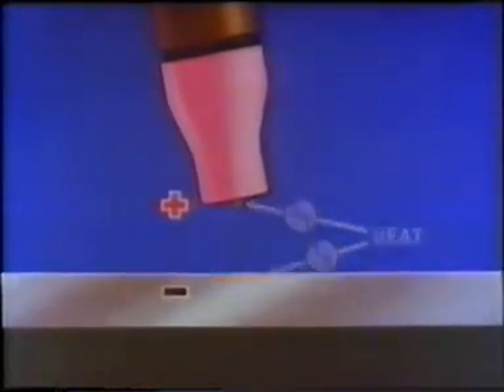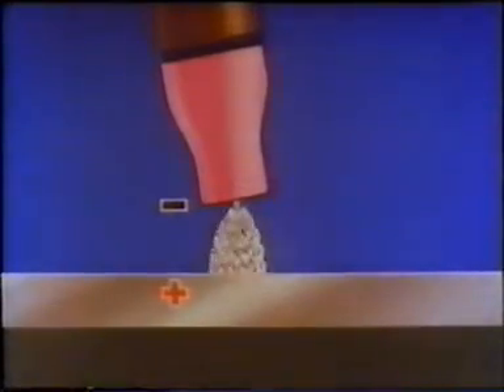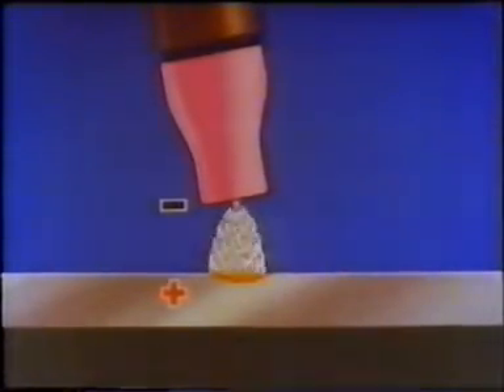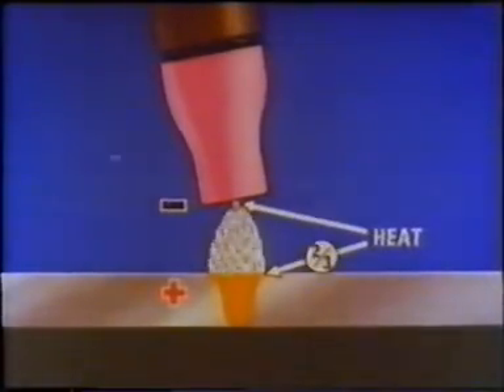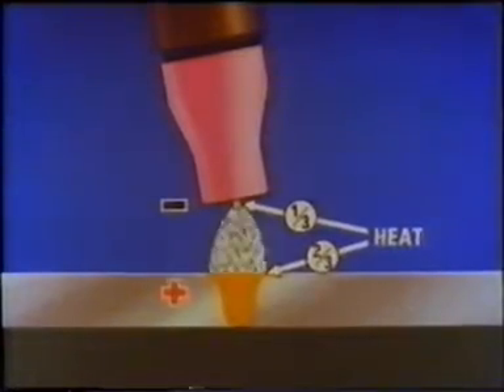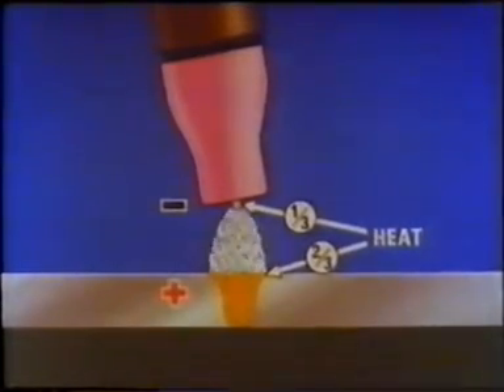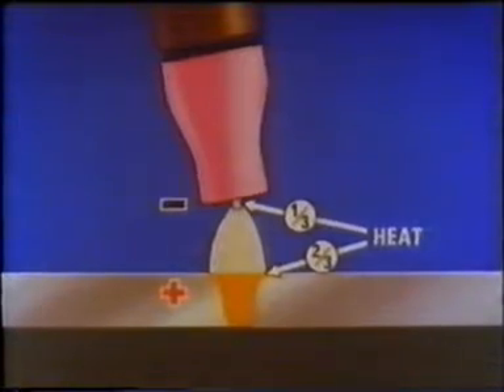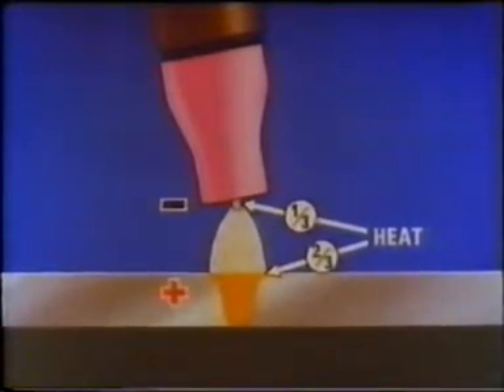With the polarity reversed, both of these disadvantages disappear. The job is now bombarded by the electron stream, so it gets hotter. Penetration is deeper and narrower. The job this time takes 2/3 of the heat. The electrode, now taking only 1/3 of the heat, is free from the risk of melting. This is the polarity used for normal DC welding. Negative to the electrode.